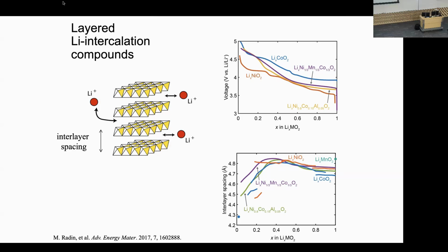And another interesting thing is the lattice parameters. They also change dramatically as you extract lithium from these materials. This here is measured from in situ diffraction. And this is the C lattice parameter, which is really the spacing between these sheets. And what you see is initially, when you pull lithium out, up to about 70% of the lithium out, this spacing doesn't change that much. I mean, it changes a little bit, but not that much. But then once you've taken out 70% of the lithium ions, the C lattice parameter collapses drastically.